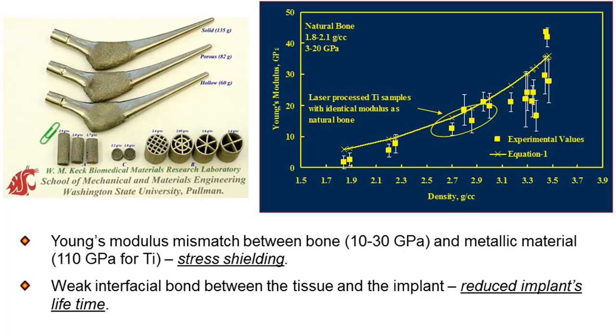There's a lot of research, for example on the titanium side, to use beta titanium alloys which have a much lower modulus than alpha-beta Ti64 alloy. Our hypothesis was, if we use technology like lens, we can actually make porous structures where the porosity is only inside - so from outside you won't see it, but inside you can have a variety of porosity. You design in your finite element analysis, decide how much porosity you need, and then make the part with that internal porosity.